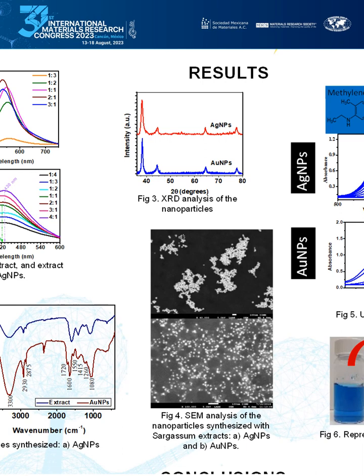Scanning electron microscopy showed that the silver and gold nanoparticles have a nanometric size with a quasi-spherical morphology. Silver nanoparticles are between 20 and 40 nanometers in size, while gold nanoparticles are smaller than 20 nanometers. In the same figures, it can be seen the organic part from the sargassum extract that is surrounding and stabilizing the metallic nanoparticles.